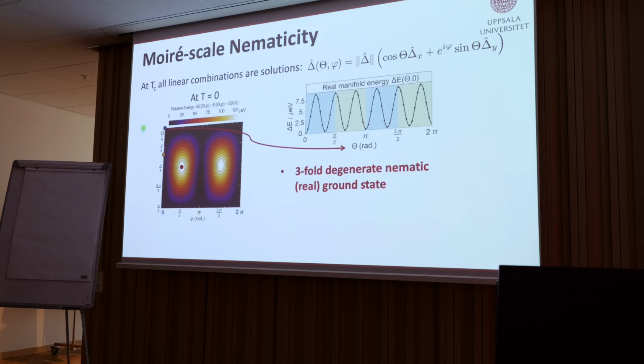But if you plot along here, you can see that in the color scheme here, it's rather small energies, but you see that you have a variation of the energies, and you have actually 3 distinct degenerate ground states. So the nematic state can point in 3 different directions, so they're all degenerate. This would be expected. You can start with a 6-fold symmetry to have that degeneracy. And it's all real. I never get a complex part in this order parameter.